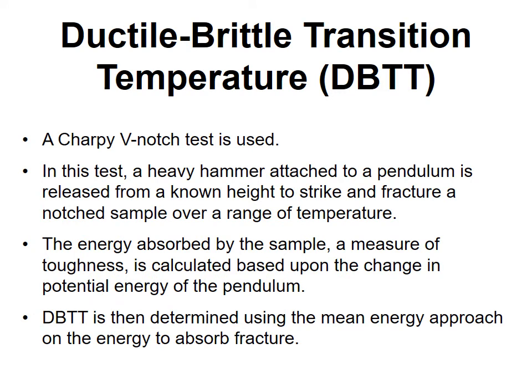Let's now look at how we can obtain the ductile brittle transition temperature, or the DBTT, of a BCC metal. The transition temperature is usually determined by using the Charpy V-notch test. In this test, the Charpy impact tester releases a heavy hammer that is attached to a pendulum from a known height to strike and fracture a notched sample over a range of temperatures. By plotting the result of the energy absorbed against temperature, the change of transition in fracture mode occurring over a range of temperatures can be found, and the DBTT is then determined using the mean energy approach on the energy to absorb fracture.